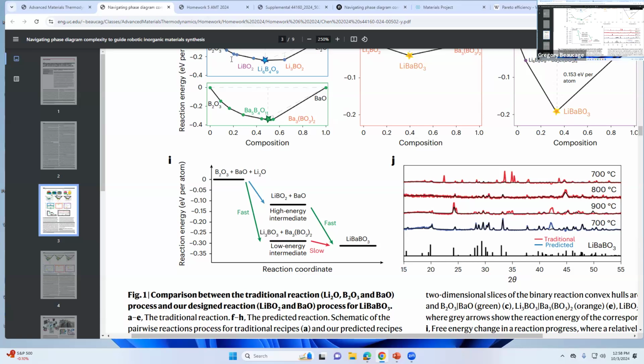So in the end, what the robot does is powder preparation, ball milling. It's got 4 steps: powder preparation, ball milling, oven firing, which would be like 8 hours, then diffraction measurement. So in total, it's going to take like 10 hours to do one sample. But it can be doing ball milling while it's doing oven firing of a different sample. So the robot can kind of amplify a little bit what it can do.